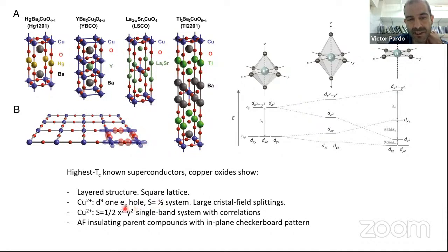The occupation of this single band occurs because of this Jahn-Teller distortion that I am depicting here. When you have an octahedral environment of the copper cation, you have this level splitting of the d levels, and when you stretch the octahedron a lot, or even when you remove the apical oxygens, these x squared minus y squared orbitals that are pointing from the cation to the anions are highly repelled, and they appear basically at the Fermi level, very separated from the rest.